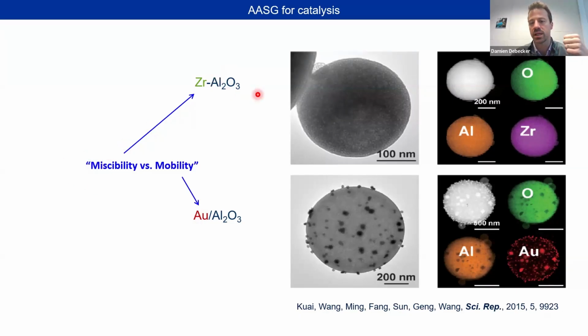It means that when you calcine this, zirconium will remain dispersed in its surrounding matrix because it is kind of soluble, miscible. So you see here zirconium that is dispersed everywhere in the matrix. On the contrary, gold does not really like to stay in the alumina, and when you calcine it, it will tend to exsolve, we call it exsolution, go out of the alumina matrix, migrate to the surface and form gold nanoparticles, which can also be interesting in catalysis.